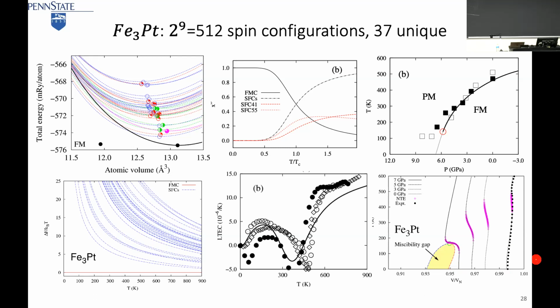So the black dots here are experiment data, just like here, but now showing the volume. The volume of the sample first increases, and then it says, oh, I'm going to increase less now, and then at the proper point it decreases, and then increases again. So each pressure is a band. You see this band here, it's a negative thermal expansion. At the critical point, the slope is negative infinity, right? A horizontal line. So that's the thermodynamic criterion, when the physical property diverges. You can define it by calculation. That's the definition of the stability.